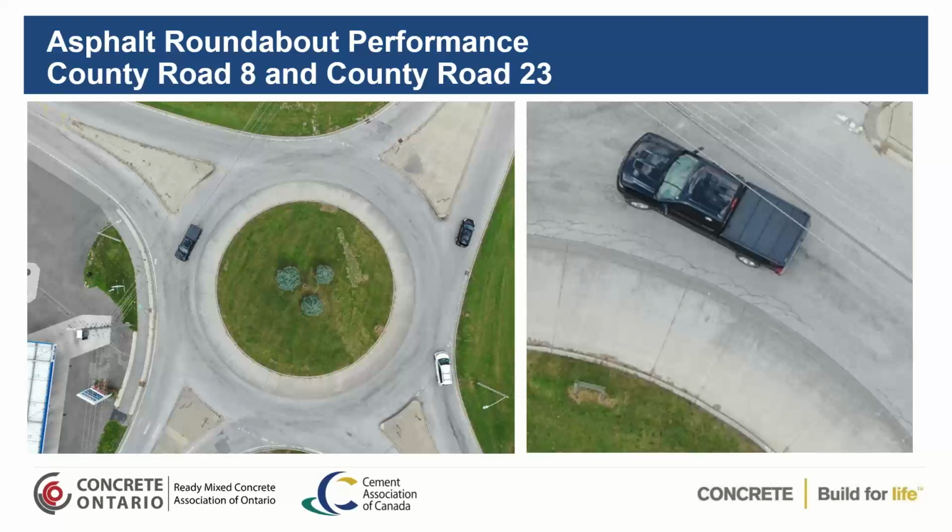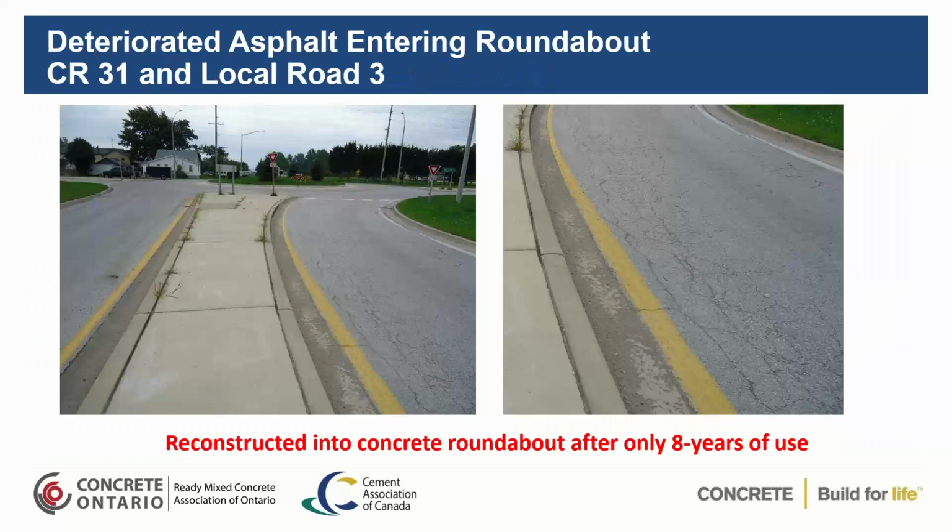There was a timeline to get all the work done, and the asphalt seemed to be the faster way to go. However, even in the photo on the left, you can see scales of gray, right? And those are stress marks in the asphalt. And then when we look at the photo on the right, you can see the aerial with the black pickup truck, and you can see the edge failure, right? You start to see this alligator cracking, which is not stopping, right? And clearly that's a bit of a problem, right? So we actually in 2010 constructed 2 roundabouts with asphalt, and you have to look at the side friction of vehicles that cause that stress, right?